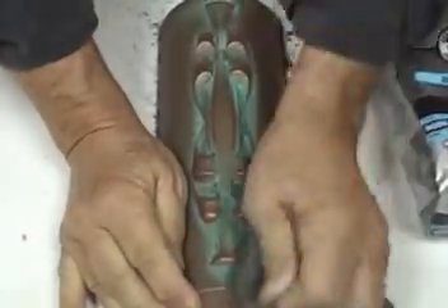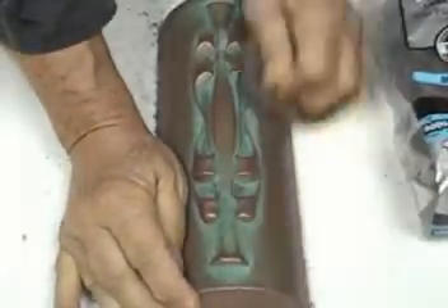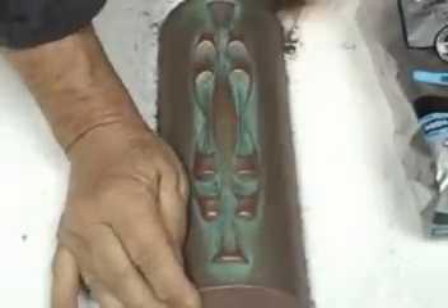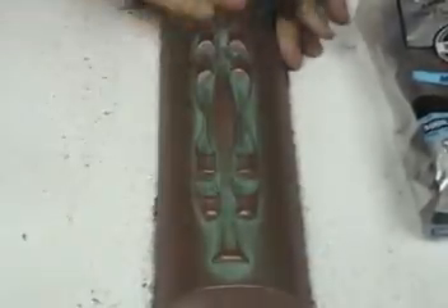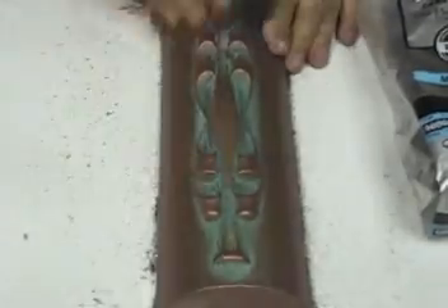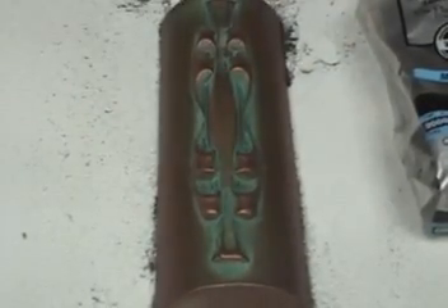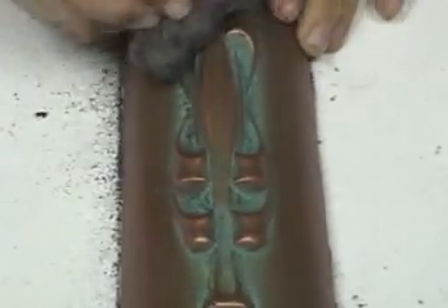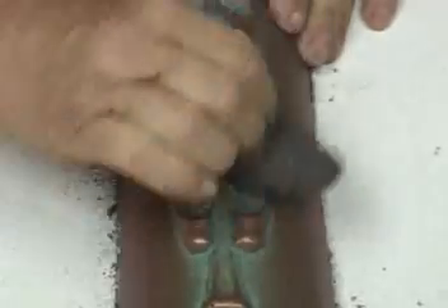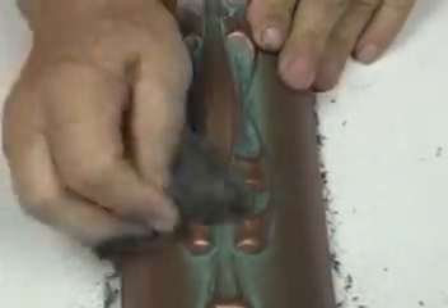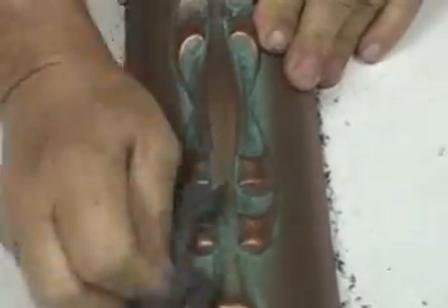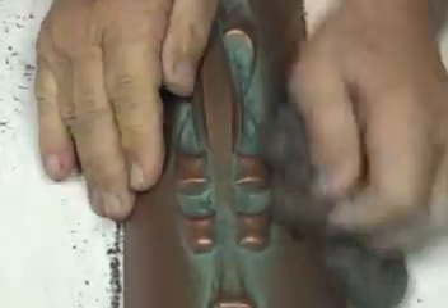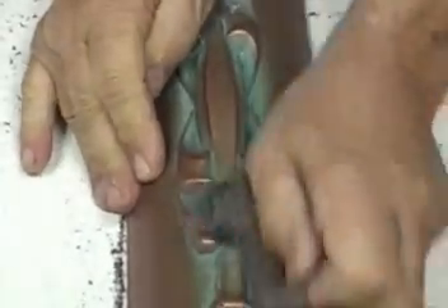Now, when we go back to buff and polish our finished C coating piece, this was the following day when we went back to sand this. We let this piece dry and let the resin component cure out for a full 24 hours before we went back to buff and polish this. And Ron is now going back with different grades of steel wool, starting with a fairly coarse steel wool and following that up with a finer and finer steel wool until we're finally using quadruple-zero steel wool to polish.